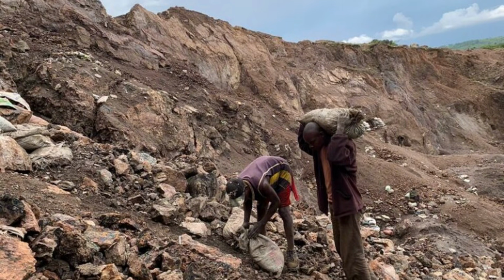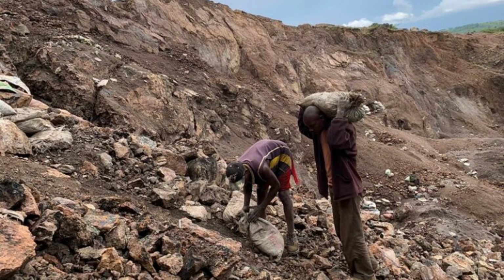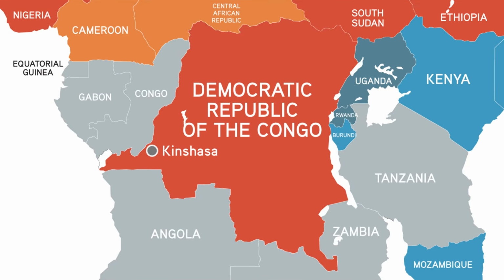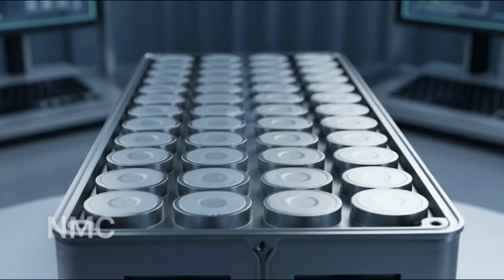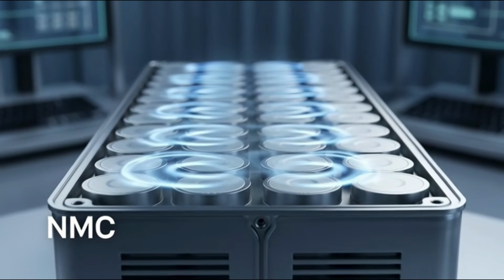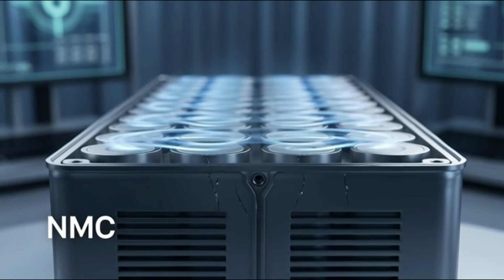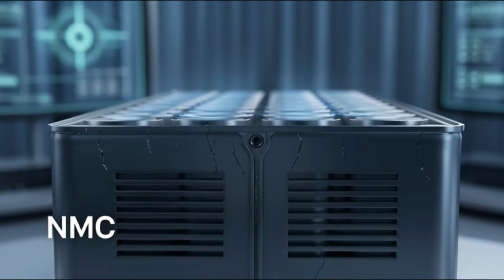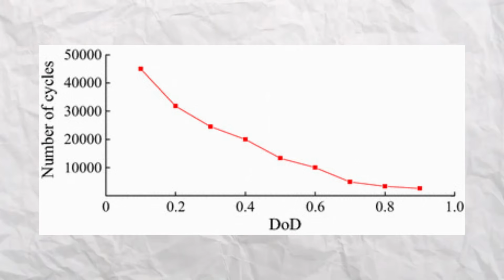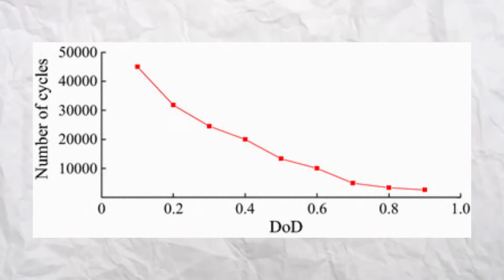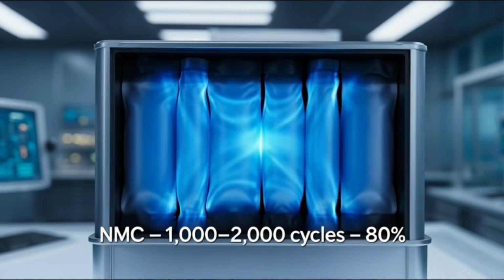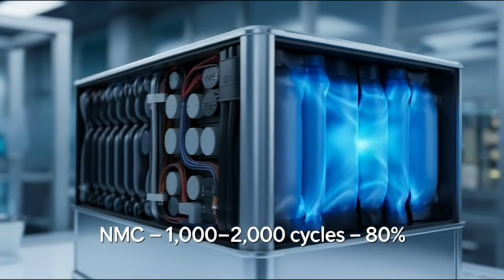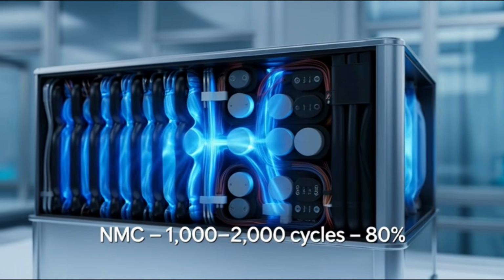Cobalt has a messy supply chain tied to some genuinely troubling mining operations in the Democratic Republic of Congo. And cobalt-based batteries still have a ceiling on how many times you can charge and discharge them before they start degrading noticeably. Typical cycle life for NMC? Somewhere between 1,000 and 2,000 full charge cycles before capacity drops to 80%.